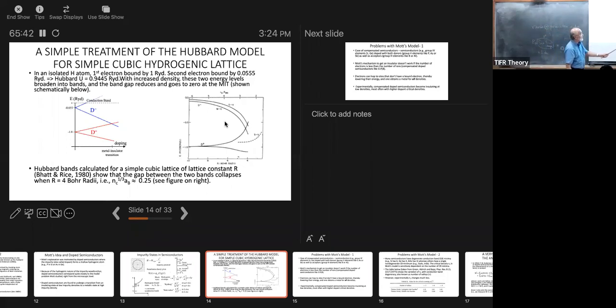Already when the distance in the cubic lattice between nearest neighbor is 10 Bohr radii, it's already come down quite a bit. So anyway, this MV and SV corresponds to multi-valley and single valley. I won't go into those details. But no matter which one you take, you find that you get a metal insulator transition roughly when the ratio of the cubic lattice distance to the Bohr radius is around 4, which is this inverse of 0.25.